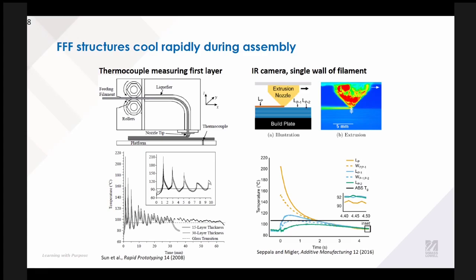And so the amount of time that's above Tg becomes really important, and that's why it's highlighted in many of our graphs and many graphs from the literature. What we see is that we've got seconds maybe above Tg, so we've got seconds where we can have flow, where we can have enough energy to have interlayer diffusion, to have that strength evolution. That is a very short amount of time, and that is really a fundamental challenge for fused filament fabrication.